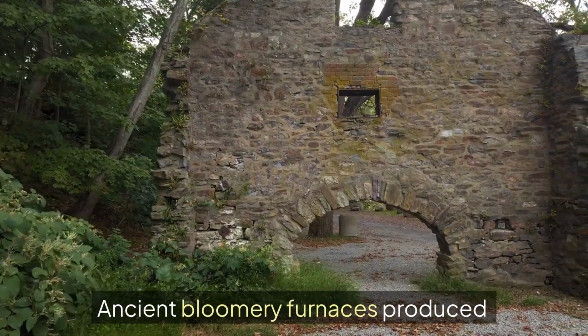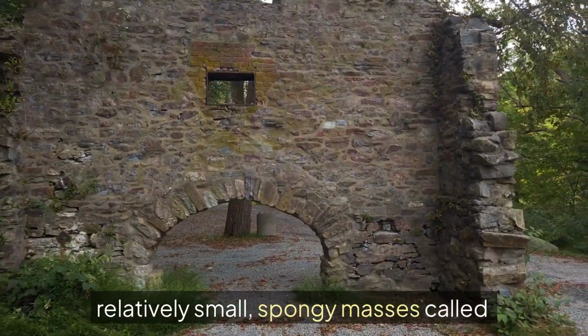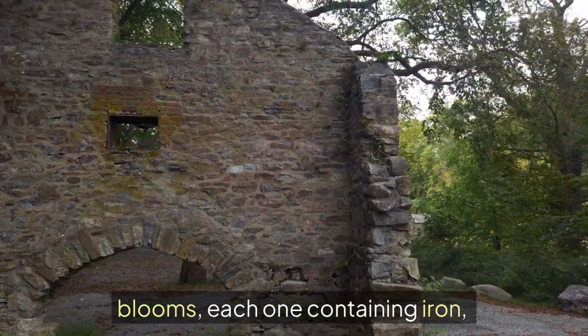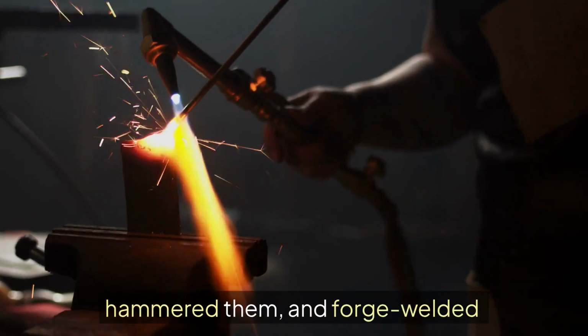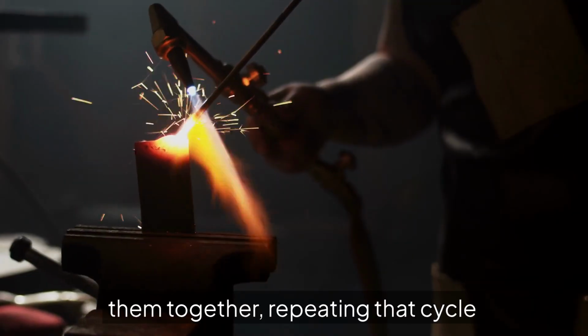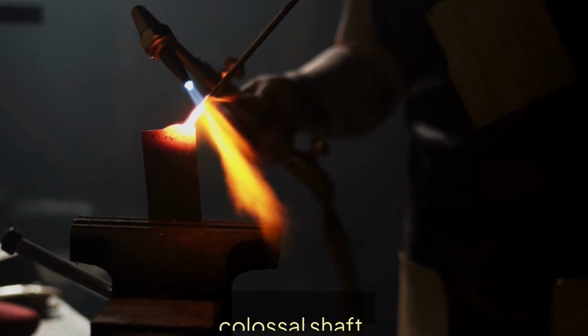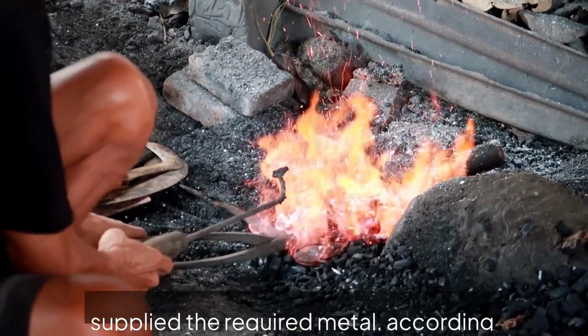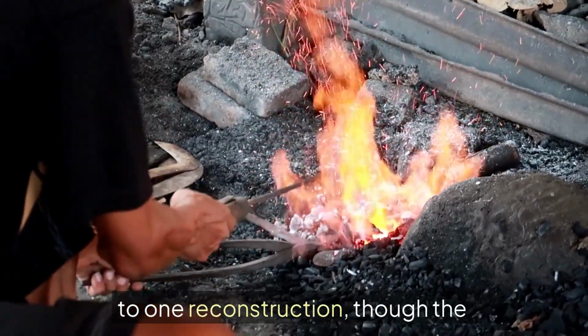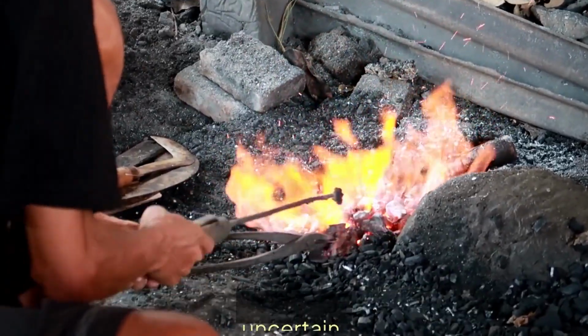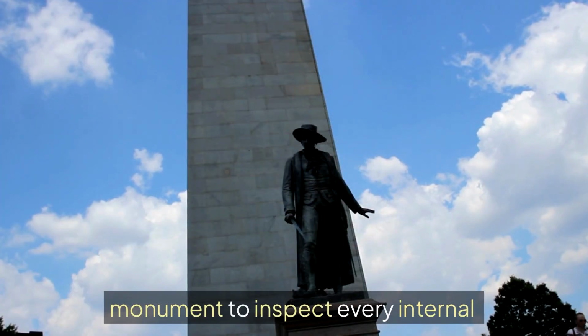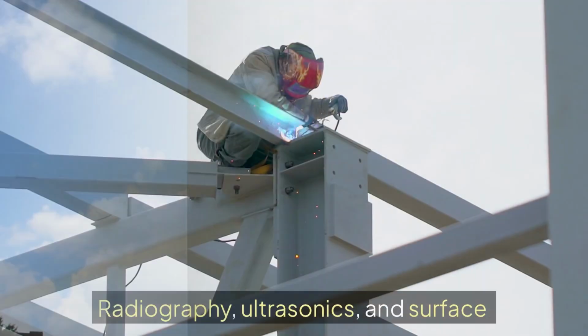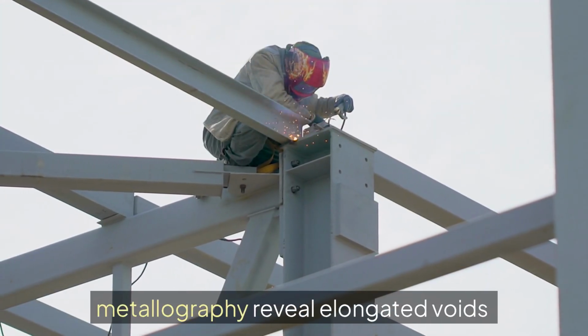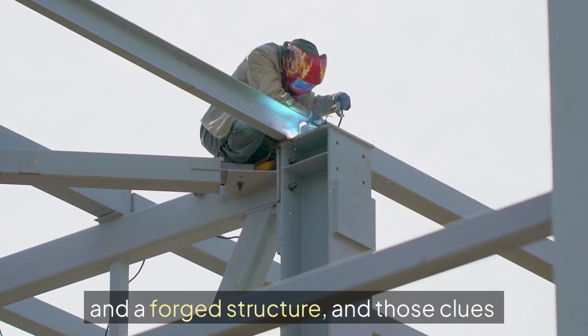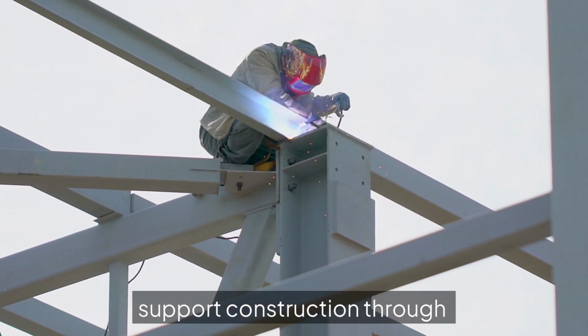Ancient bloomery furnaces produced relatively small, spongy masses called blooms, each one containing iron, unreduced ore, pores, and trapped slag. Smiths reheated those pieces, hammered them, and forge welded them together, repeating that cycle until separate masses became one colossal shaft. Hundreds of furnace heats may have supplied the required metal, according to one reconstruction, though the exact workshop sequence remains uncertain. You can't dismantle a protected monument to inspect every internal joint. Radiography, ultrasonics, and surface metallography reveal elongated voids in a forged structure, and those clues support construction through repeated welding